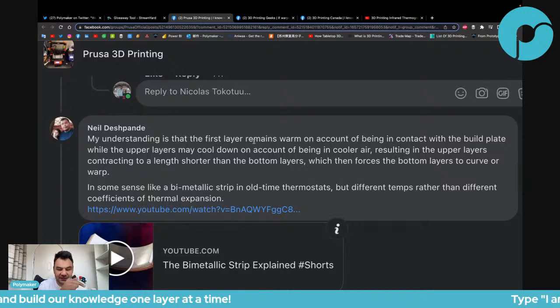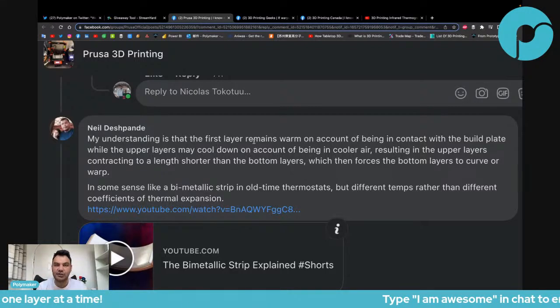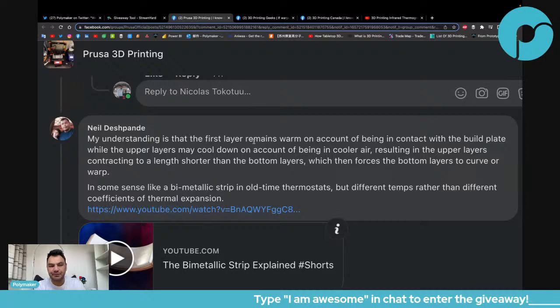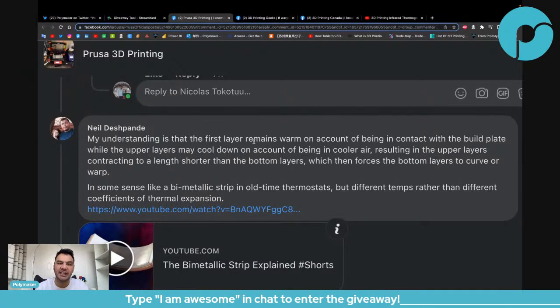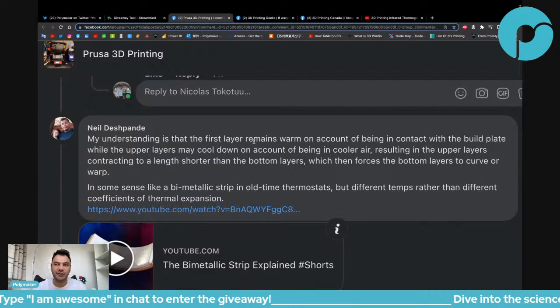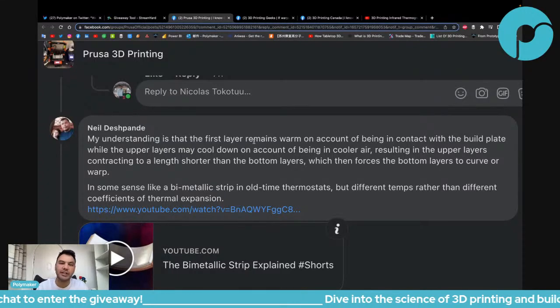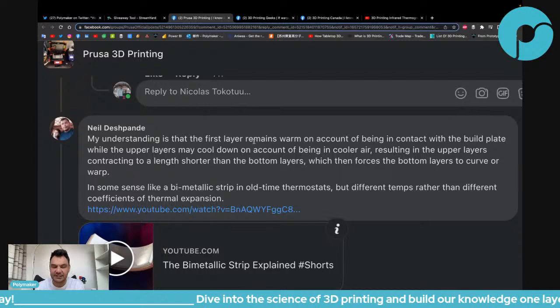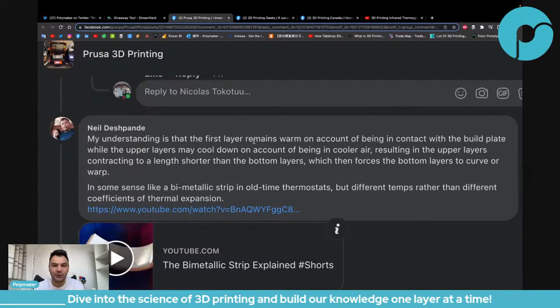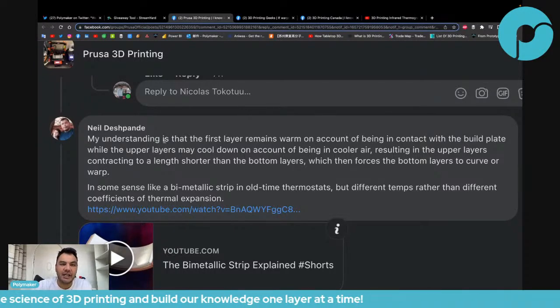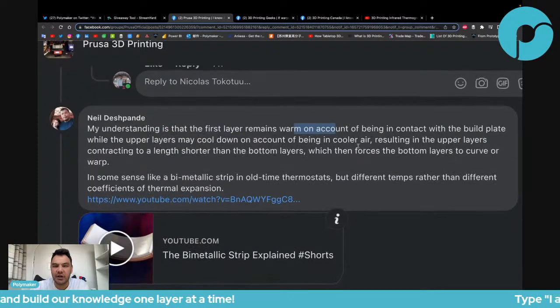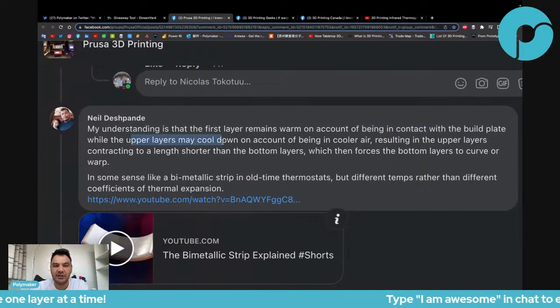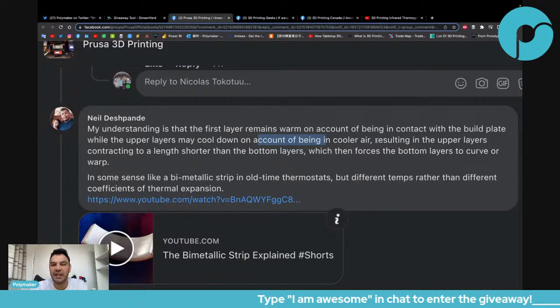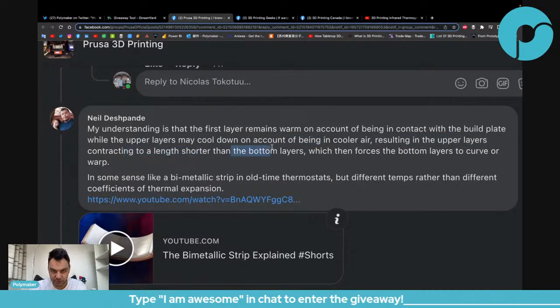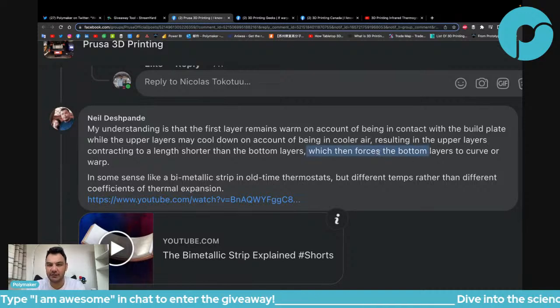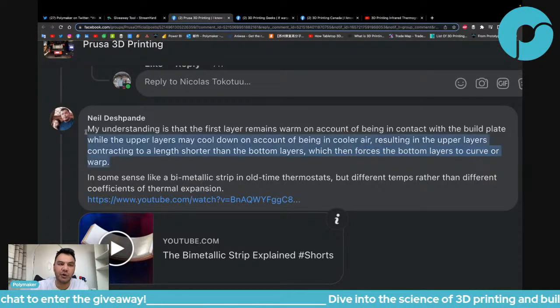If it's single string by single string, you know what I mean? It's some shortcut in the explanation that I don't like. It's fine to take a shortcut, but I will always be the one that says, okay, you have taken that shortcut. Can you please take me through the long journey on why we go from here to there? My understanding is that the first layer remains warm on account of being in contact with the build plate, while upper layers may cool down in the cold air, resulting in upper layers contracting to a length shorter than bottom layers, which then forces the bottom layer to curve and warp.